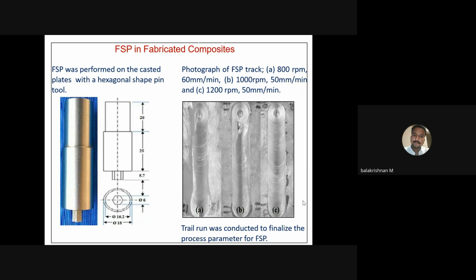Here we can calculate the parameters like traverse speed, RPM, etc. with the help of design software, design of experiment software. But even though the process was carried out on the casted composite plate, so I went for a trial and error method. In that method, 1000 rpm 50 mm per minute, and 800 rpm 60 mm per minute, and 1200 rpm and 50 mm per minute were used for friction stir processing to conduct the trial run.